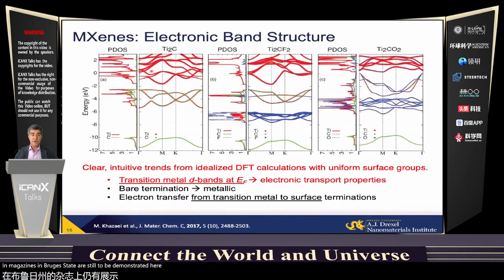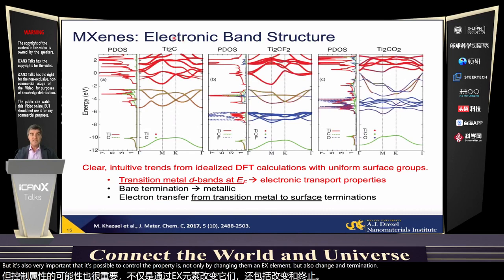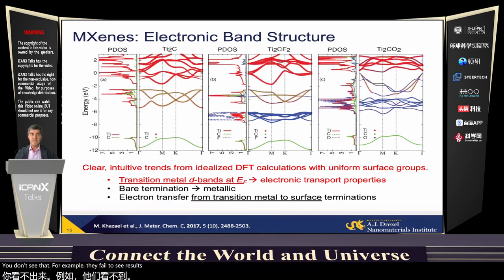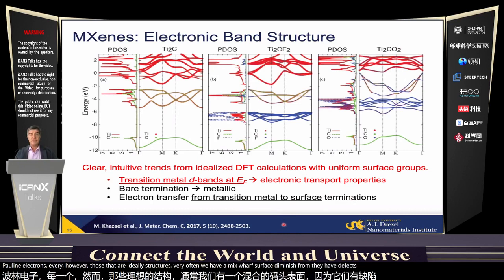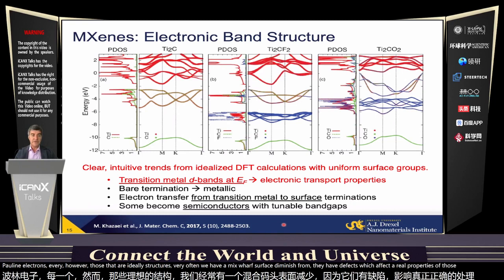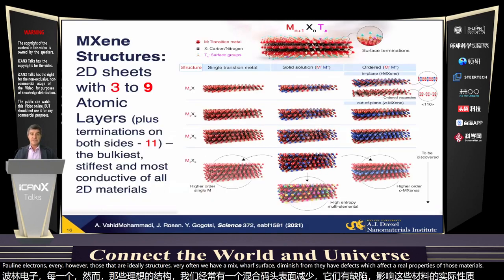But it's also very important that it's possible to control the properties not only by changing the M and X elements, but also by changing terminations. You will see that, for example, titanium 2 carbide without surface termination will have a high density of states at the Fermi level, and it will decrease with fluorine termination, and actually a band gap can be opened by terminating the surface with oxygen, pulling electrons away. However, those are idealized structures. Very often we have a mix of surface terminations. We have defects which affect the real properties of those materials, leading to very different properties.